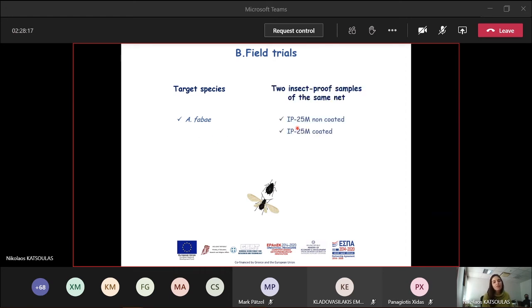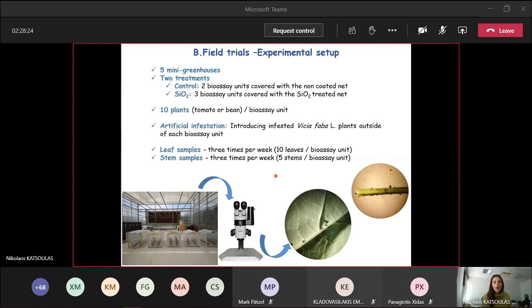Now I'm going to present the methodology followed in the field trials, in which the target species was only Aphis fabae. In this case, we tested an insect-proof net of 25 mesh size against this insect. In this experimental setup, we used 5 mini greenhouses. 2 of them were covered with non-coated nets, while the other three were covered with coated nets.